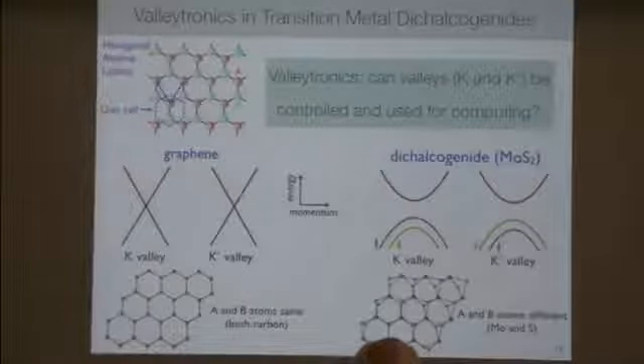And early on in the days of graphene, it was thought that perhaps graphene would be a good candidate for this pursuit. But in graphene, the A and B atoms are identical. They're both carbon. And this symmetrical property of graphene is largely responsible for many of its unique electrical properties, but it means that it's difficult to distinguish the valleys from each other. But in the dichalcogenides, the A and B atoms are different. The A atoms are molybdenum and the B atoms are sulfur, for example. And then there's some hope that the valleys could be distinguished in these materials.